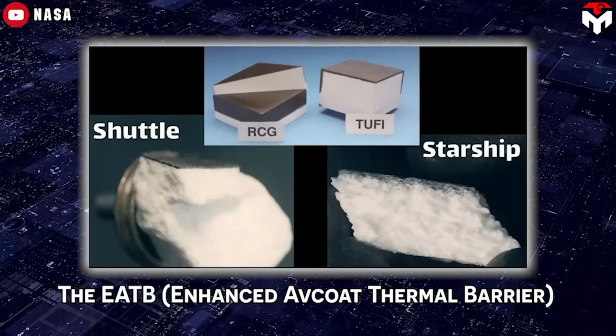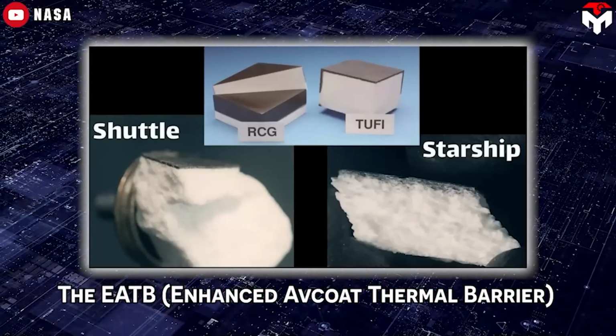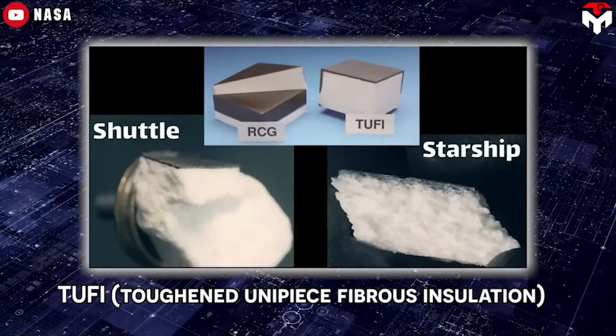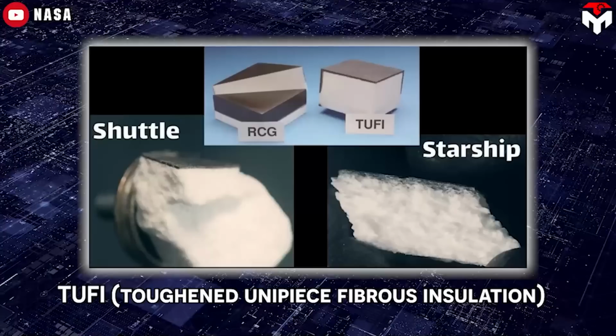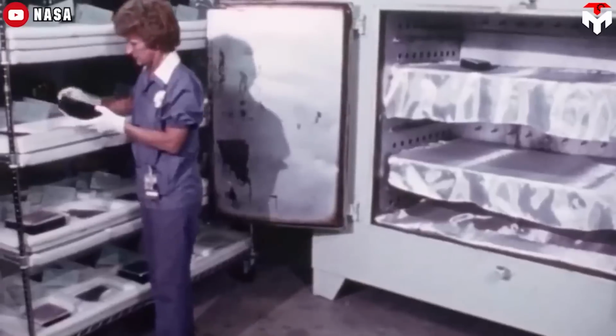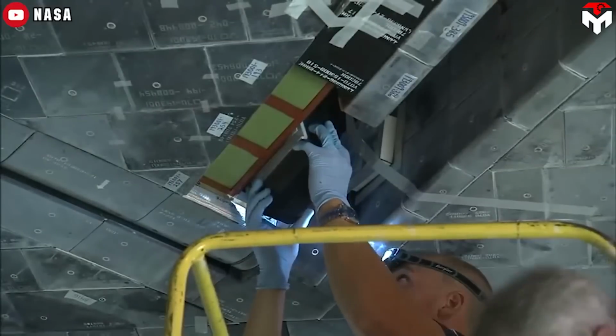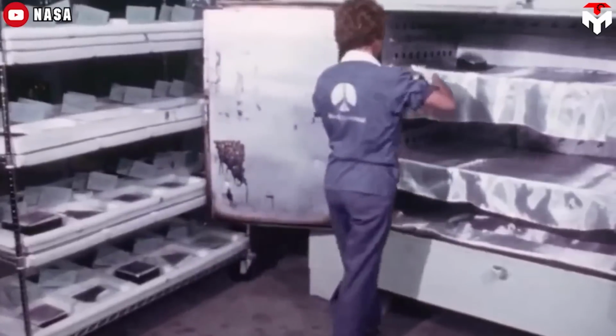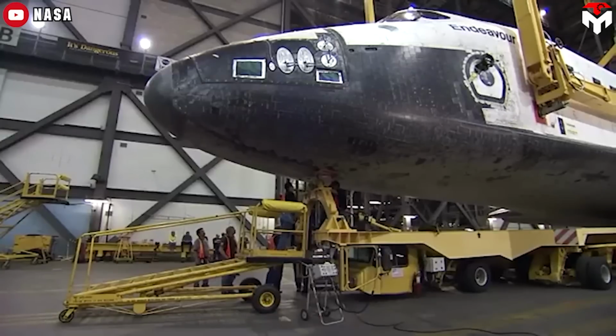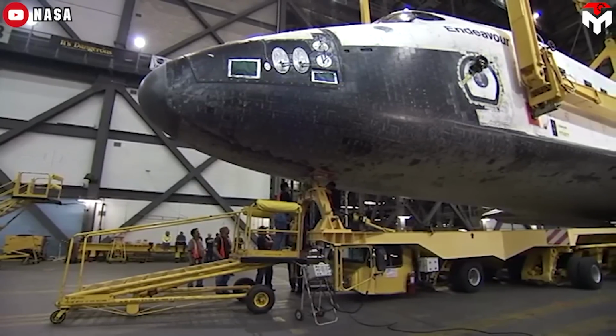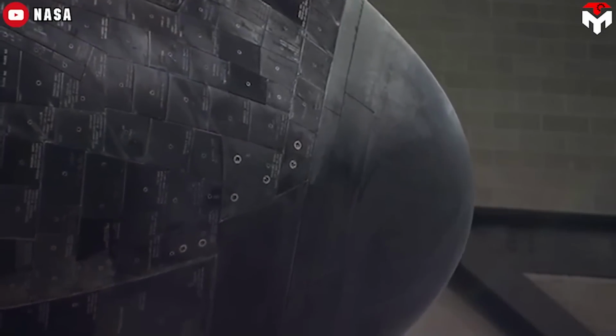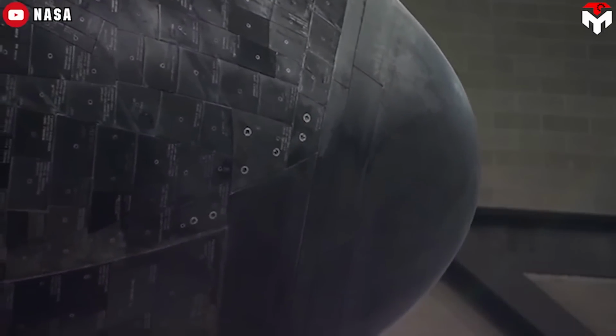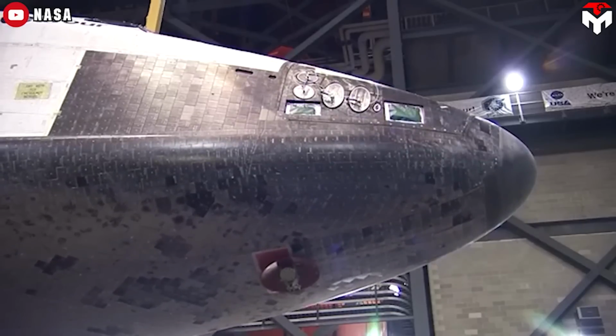The EATB Enhanced Avcoat Thermal Barrier tiles with TUFI toughened unipiece fibrous insulation coatings with added molybdenum disilicide, which were introduced in the later years of the Space Shuttle program, were known for their improved durability and performance compared to earlier tile designs. The reason why few TUFI tiles were used on the shuttles is due to weight concerns. TUFI is less fragile than the older RCG reaction-cured glass coating, but also heavier.